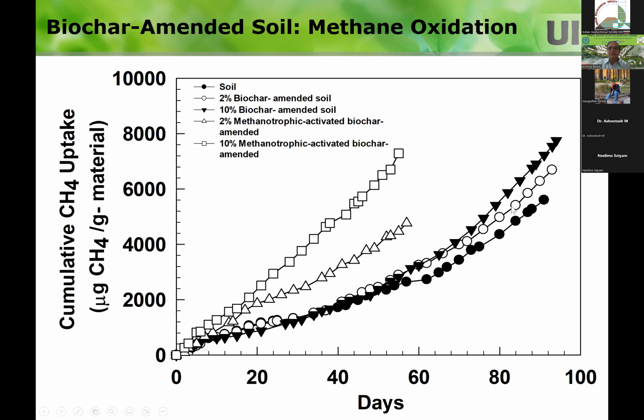After that, you see that the oxidation is higher than the soil. And then when you add more, 10% biochar, again you need time for the methanotrophs to acclimate, and after that you see it deviates. So you don't expect the methane oxidation to increase right away. It takes some time for the methanotrophs to acclimate, and then you see this. At the end, this is not really a short-term test. When you put the cover on and walk away, that cover is going to be there for years and years.